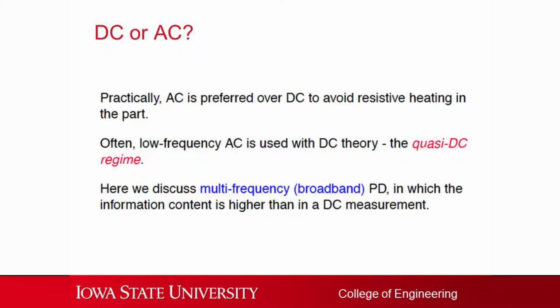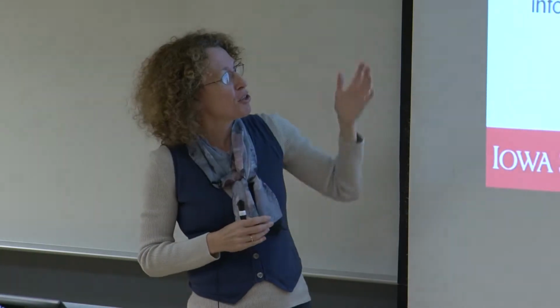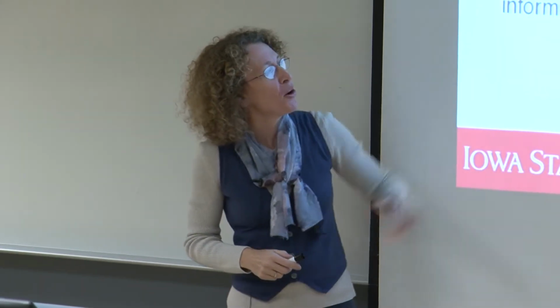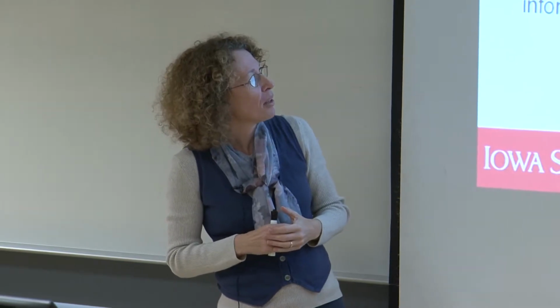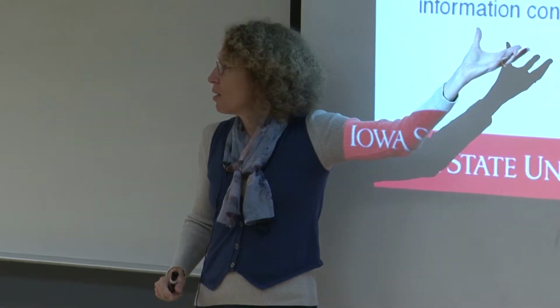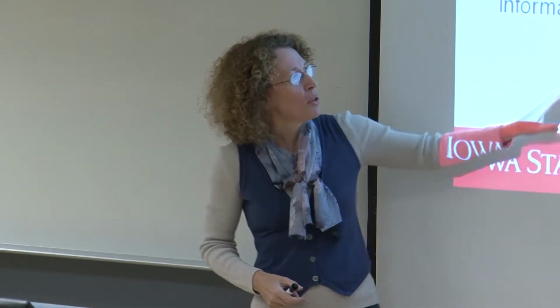As I mentioned before, historically speaking, this probe has been used with mostly a DC or quasi-DC type of current, but practically we prefer AC because it avoids resistive heating in the part. Now, often people use a low frequency AC current, but they interpret it using a DC theory, and usually that's okay, as long as you're in the right part of the theoretical regime. But what we did was we actually took that technology, we kind of expanded it in terms of using higher frequencies, because we can get more information that way.